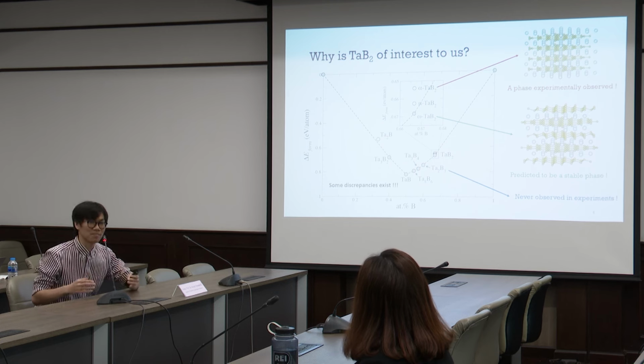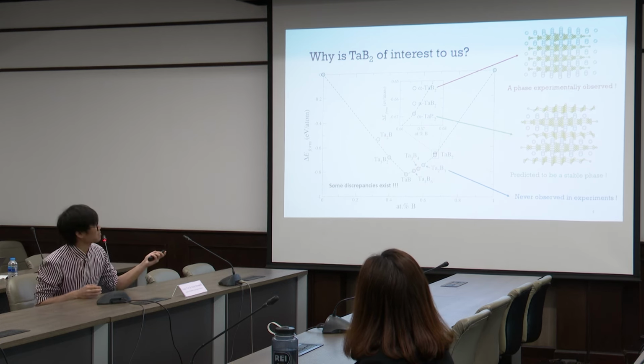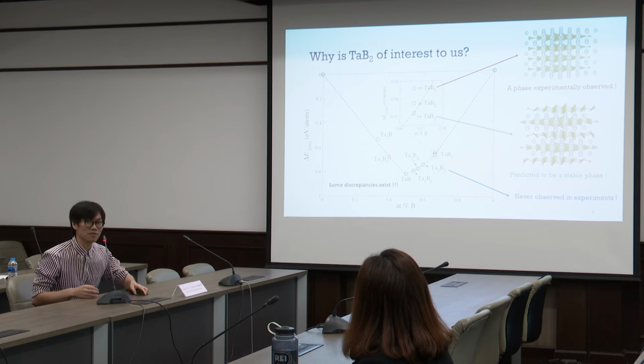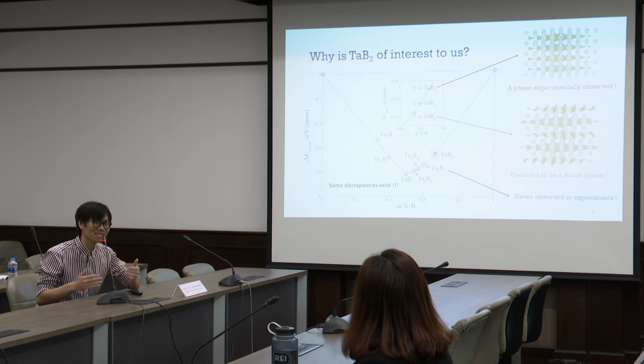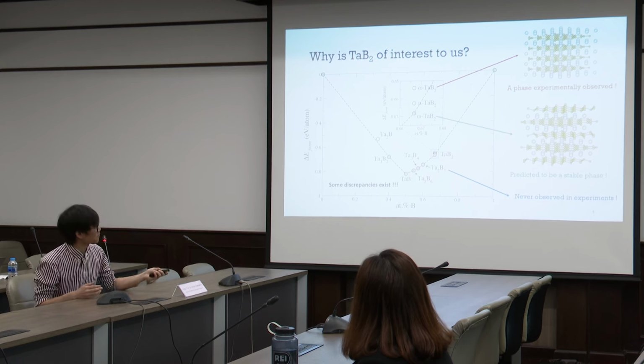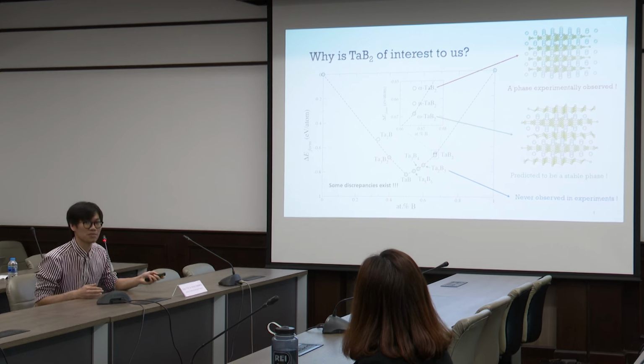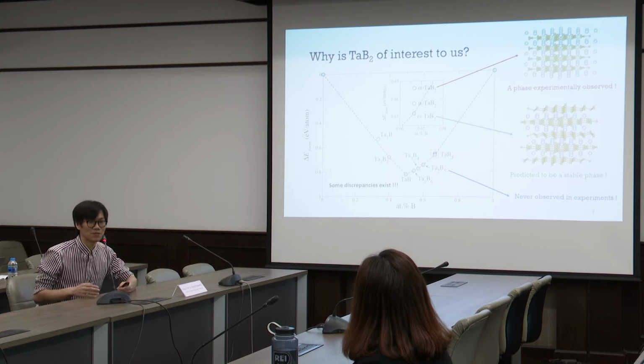So there is some discrepancy in this material system. And also, for Ta3B2, the theory predicts that this one should be thermodynamically stable, but we have so far never seen this phase in any experiment. So in this work, I would like to address this issue.